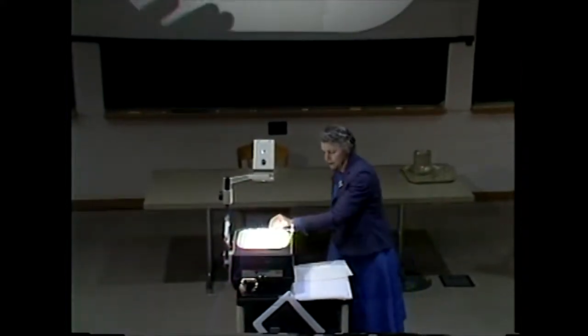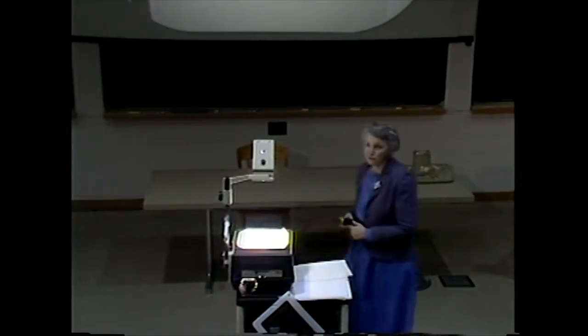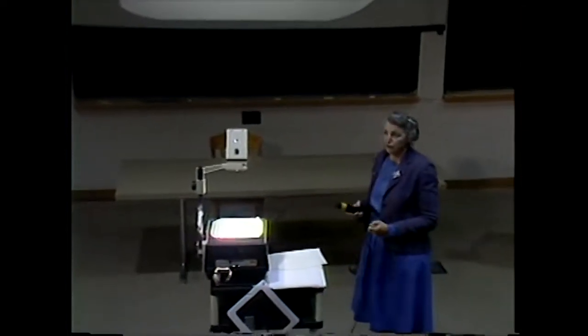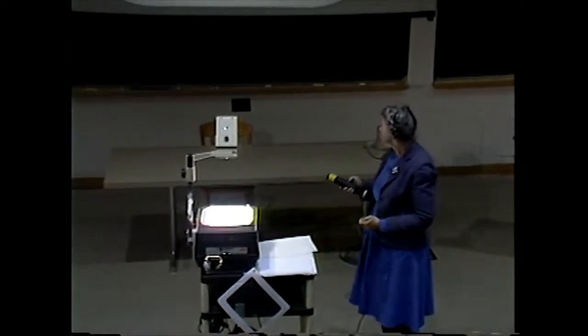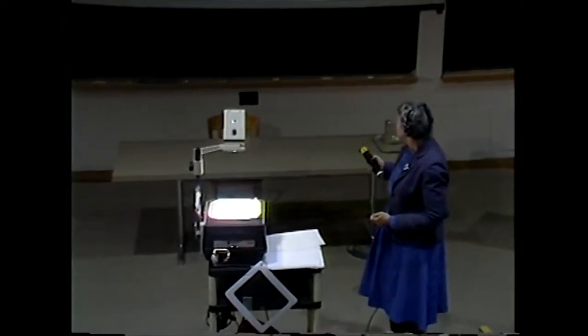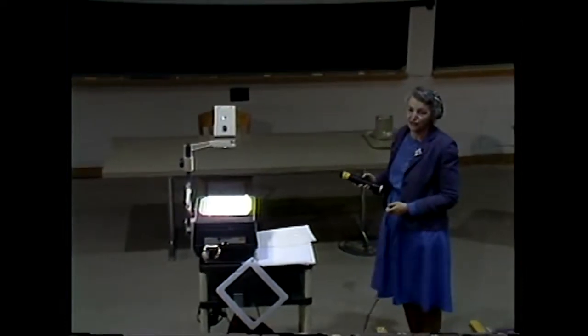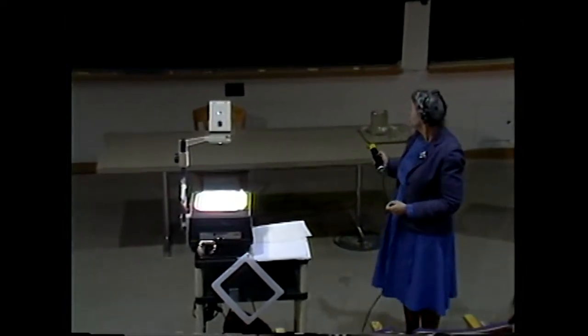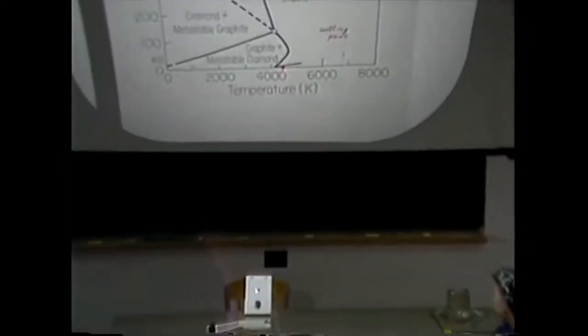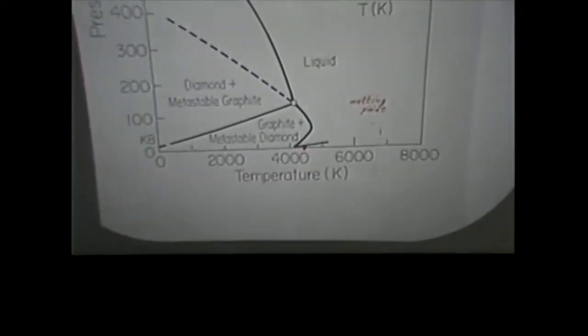And where do we sit on the graphite phase diagram? Here's the graphite phase diagram, a very historical phase diagram, the phase diagram of Bundy that has to do with the formation of diamonds. And so here's the diamond phase. That was what this phase diagram was concocted for. But we're over here at very low pressure but high temperature, and we're going to melt carbon. At least we think we're going to melt carbon.